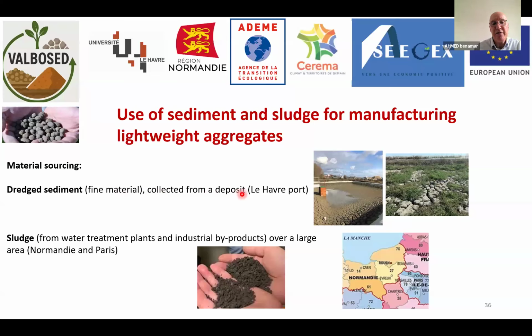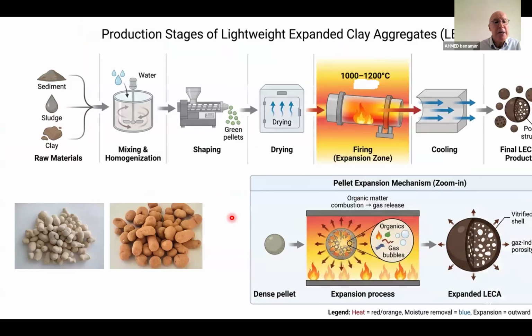So the dredged sediment for this project was collected from the second deposit we showed before, which is the smaller one, and the sludge was collected from water treatment plants and industrial byproducts, which are rich in organic matter or carbon over the large area of Normandy and Paris. The process of firing: we mix the materials, which were shredded and dried before being fired, then cooled. So this is an example of the first aggregates which were fired.